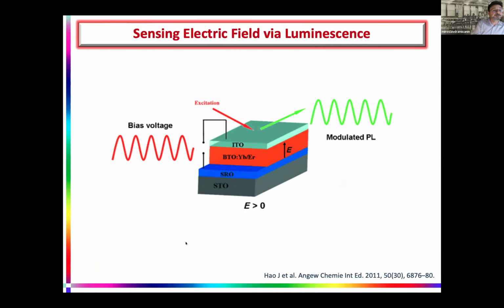So the next example is how to measure electric field with non-contact, optical measurements, via luminescence. Actually, it's not the results of my group. It's taken from the literature. What is important, I will later tell you why it was so important for our group, but we still didn't manage to start working on this type of material, is that if you have a ferroelectric material like barium titanate, and you dope it with trivalent lanthanides. This is ytterbium-erbium, a very famous upconversion pair. Ytterbium absorbs and erbium emits in the green and red spectral range.